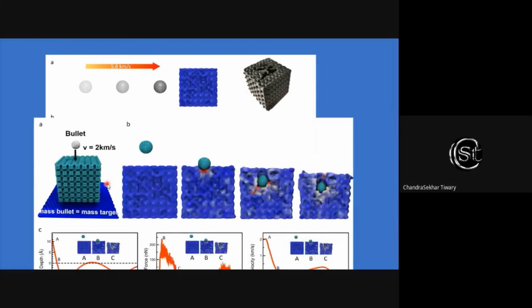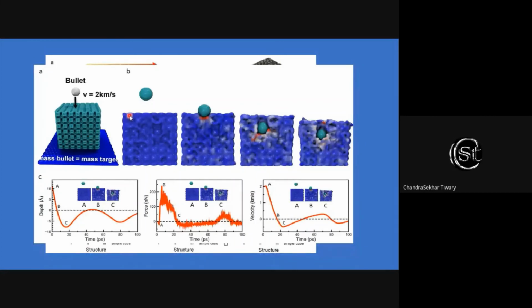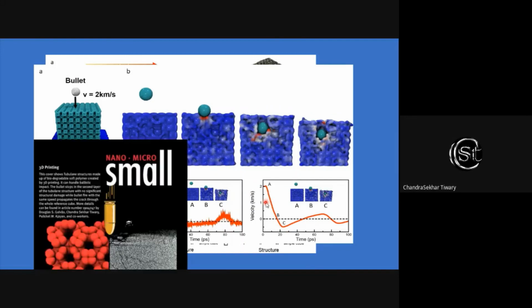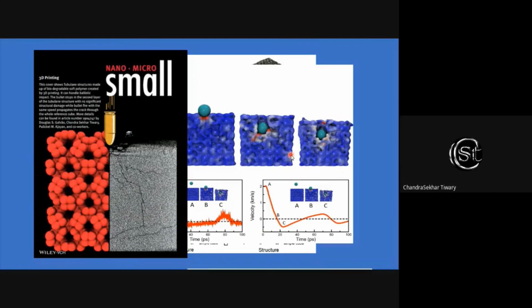Now, when we do simulation, just to understand what happens, what we clearly see in the MD simulation is, if you hit the structure with this topology, you can clearly see the bullet gets trapped because of the topology. At the same time, locally this structure or polymer can melt, but it doesn't transfer all the heat because it's a bad conductor of heat. It melts locally, still it doesn't allow the crack to propagate, and the bullet doesn't affect the lower part of the structure. And we have done a detailed study of this structure, which is shown in the figures, and the details are mentioned in the paper. And this was on the cover page already.